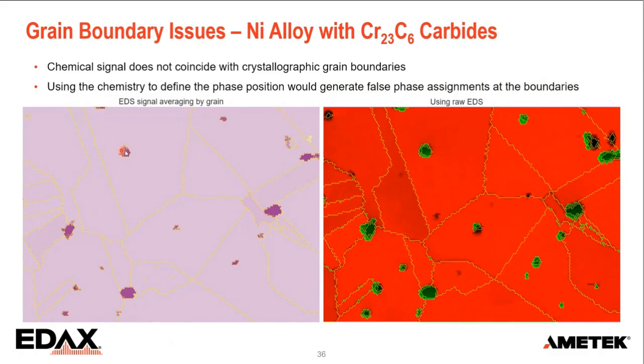chemical shift or chemical change between the particle and the grains around them. And that allows you to get a very sharp phase discrimination and orientation discrimination at particles, even when they may be smaller than 1 micron, which is often shown as, let's say, an average interaction volume for EDS.